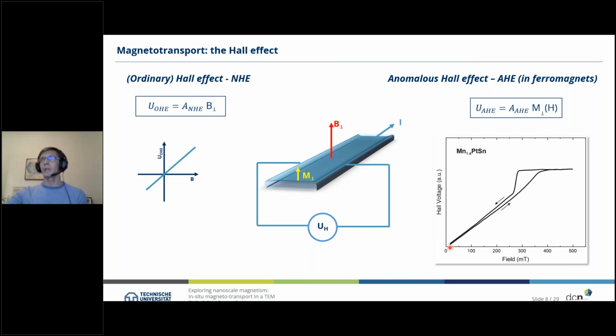So you see the Hall voltage as a function of the applied magnetic field. And you can see for that sample, it linearly increases up to the saturation of the sample, and then with the hysteresis comes back to 0. So with this technique, we can now measure the magnetization of our sample as a function of the magnetic field. As you see, we need to apply a magnetic field in order to measure the hysteresis of our sample.